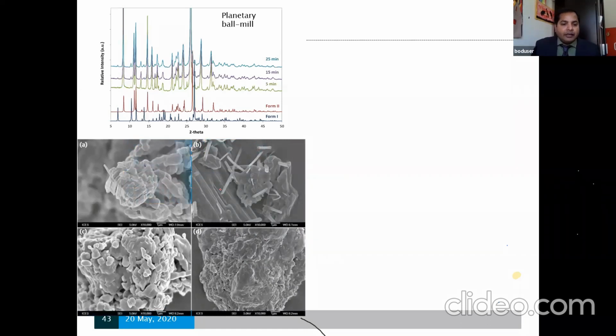These are the scanning electron microscopy images. You could see this is the scaled up co-crystal of caffeine glutaric acid. When you milled the sample for 5 minutes, you could see there are already form 1 needle shaped materials. If you look further, by 15 minutes you could already see there is a polymorphic change. These two were taken at 25 minutes. There is a significant amount of phase impurity.